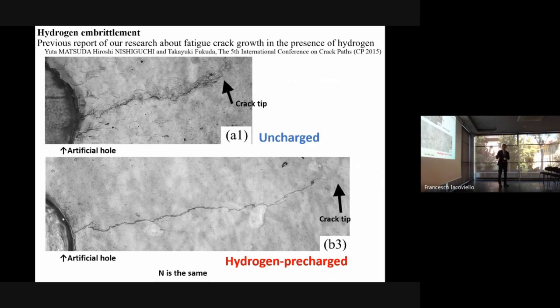This slide shows the previous report of our research about fatigue crack growth that was presented in the 5th International Conference on Crack Paths. So this picture shows cracks from an artificial hole, 0.5 millimeter diameter. Okay, this is the uncharged one. This is in the presence of hydrogen. In the presence of hydrogen, the number of fatigue cycles is the same, but the crack propagates longer than that of the uncharged one and sharply propagates. From this picture we can see hydrogen affects crack propagation.